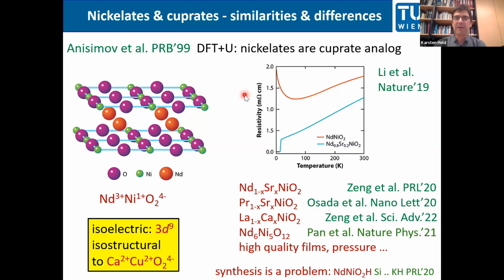Now, as for theory, we have actually to go 20 years back when Anisimov, Bukhvalov, and Rice predicted nickelates to be superconducting. They did DFT plus U calculations, and just from the apparent similarity to cuprates, they concluded nickelates should also be superconductors, or at least are very good candidates for that. This similarity includes the crystal structure, which is actually the same as that of the simplest, but maybe not best, cuprate superconductor, calcium copper O2.